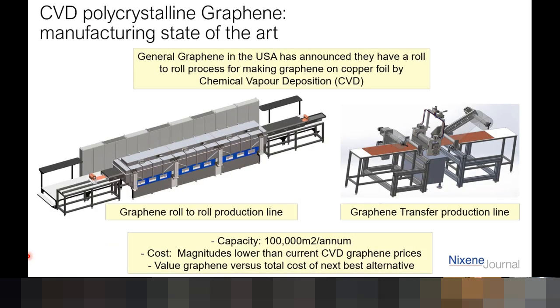Next slide, please, Mike. This is in the States, a company called General Graphene. The machine there on the left-hand side is a similar reel-to-reel machine, but this time it's horizontal, and the grey bit in the middle is the furnace. The whole thing is about 14 meters long, which gives you an idea about the scale. Then they can make graphene on the copper foil, but they've also got a graphene transfer line where they can take the graphene off the copper foil by a separate process and transfer it onto other substrates. They've already got the capacity as of next month to make 100,000 square meters per year. And they're talking about having 1 million square meters per year capacity next year, in 18 months. This is industrial scale manufacture by anybody's benchmark. Next slide, please, Mike.